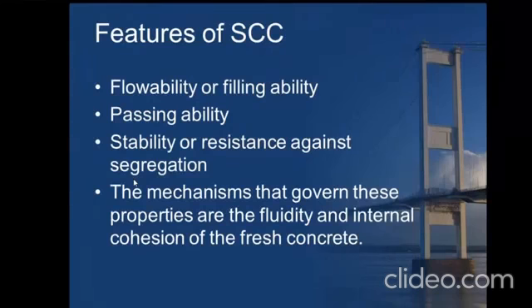The next main thing in terms of self-compacting concrete that we have come across in practice is segregation. When we are not able to get a good blend of self-compacting concrete, there is a major problem termed segregation, where the aggregate separates from the mortar, and that is a big problem. The sole purpose of using self-compacting concrete, as I told, is that I don't need a vibrator. But when segregation occurs, it is a very tedious job to make it work in practice. I'm talking about when we come across this after placing the concrete at the site. So a thorough mix design of the self-compacting concrete in order to prevent this segregation plays a major role, right?